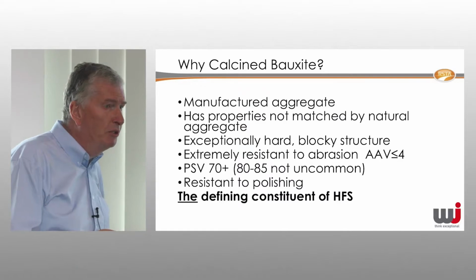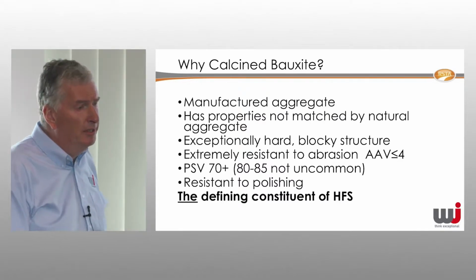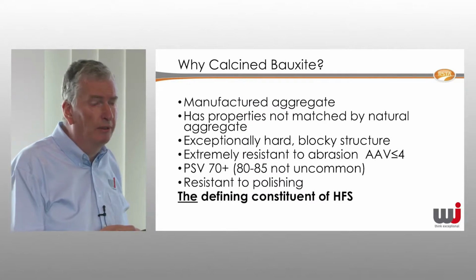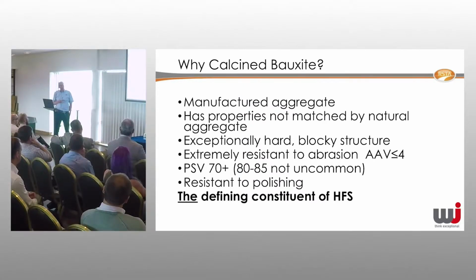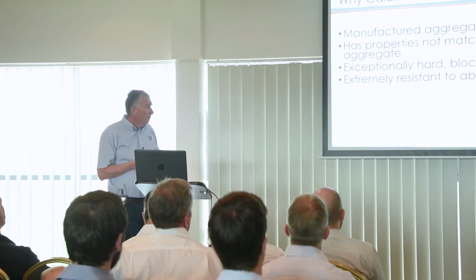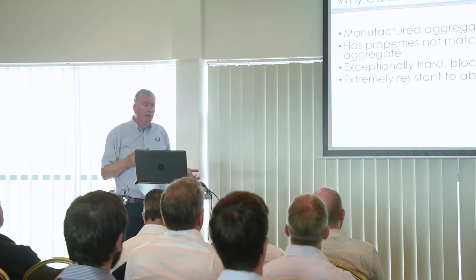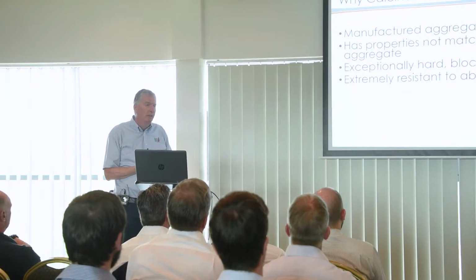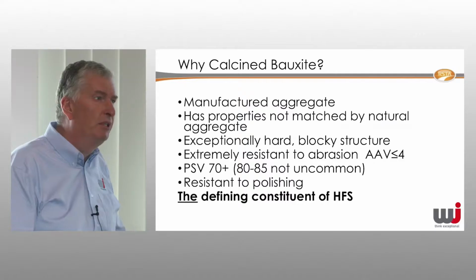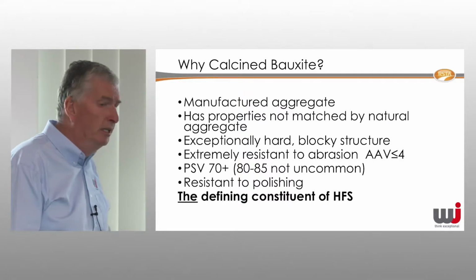So why calcined bauxite? Well, it's a manufactured aggregate. It's produced in factory conditions from bauxite clay that's quarried out of the ground. It's got properties that are not matched by natural aggregates. It's very blocky in terms of its shape. It's very angular, cubical in a way. It's extremely resistant to abrasion. The aggregate abrasion value is less than 4. High is bad, low is good in AAV terms, and there are bauxites on the market now of less than 1, which is exceptionally hard, and they're approaching diamond in terms of their hardness. That's how hard they are. So they do resist wear very well.